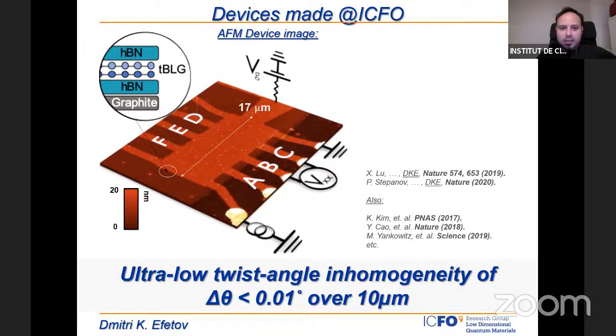Just to give you an idea of how the devices look that we make in our lab: this is an AFM image of a typical device. We shape those Hall bars of magic-angle graphene. And what's also important is that these Hall bars consist of a quadruple layer of van der Waals materials. We usually have a graphite layer underneath it all, and graphite we just treat as a metal.